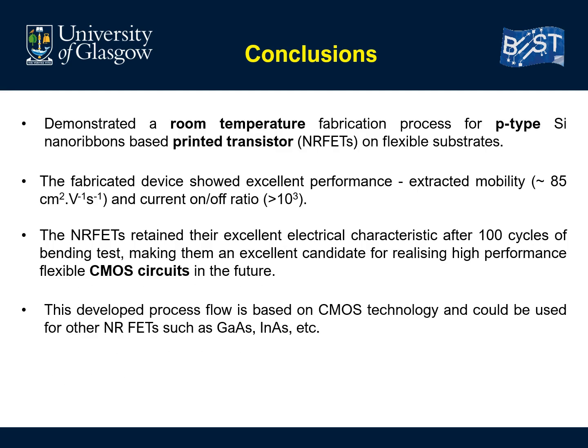a room temperature fabrication process for a p-type silicon transistor on flexible substrate, and the p-type silicon nanoribbon-based FET showed an excellent performance even under cyclic bending tests, making them an excellent candidate for realizing high-performance flexible CMOS circuits. The optimized process flow is based on the CMOS technology, and it could be extended for other nanoribbons based on other high mobility materials to realize field effect transistors, such as gallium arsenide, gallium nitride, and indium arsenide, etc.